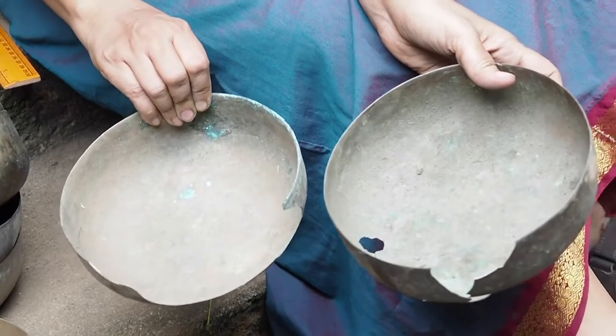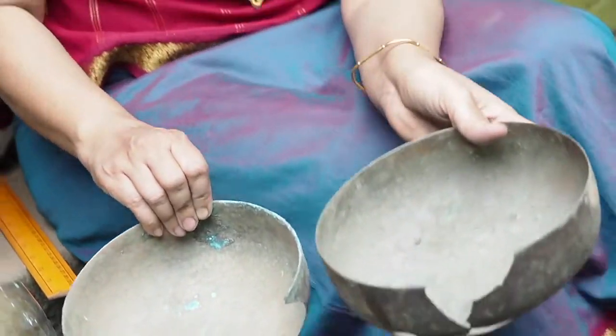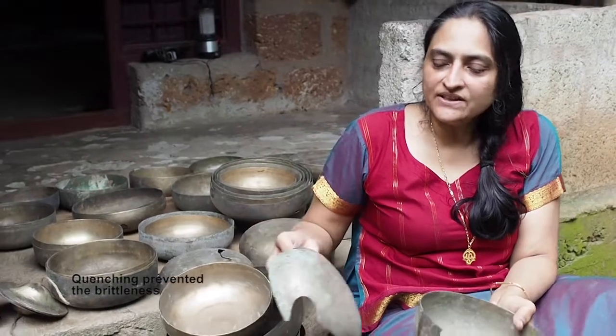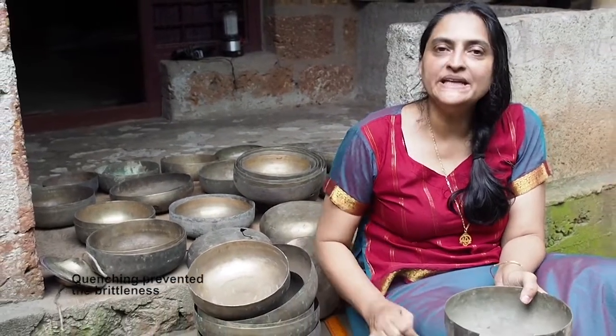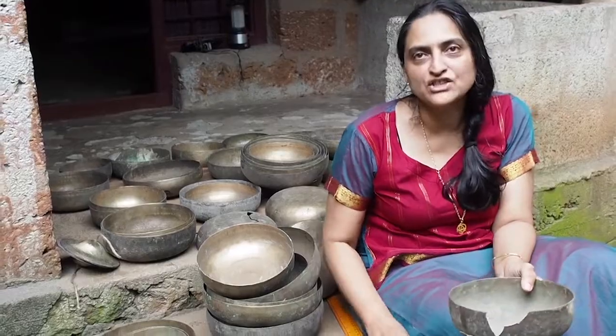But I will also add that the quenching process was essential because by quenching the metal at the end of the forging process, the quenching is what prevented the formation of the brittle delta phase. The quenching process is actually what made the metal less brittle than it would have been. So the quenching is done to prevent the embrittlement, and that was why they're called wrought and quenched high-tin beta bronzes. And we saw them doing the quenching process for the cymbals, where they dipped it in the water for a few seconds. And that is really what helps to prevent the bronze from being as brittle as it might have been had it not been quenched.